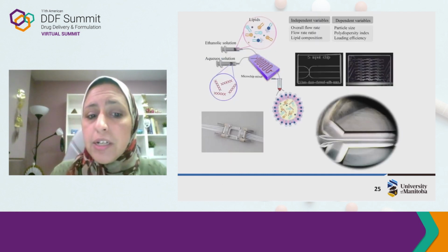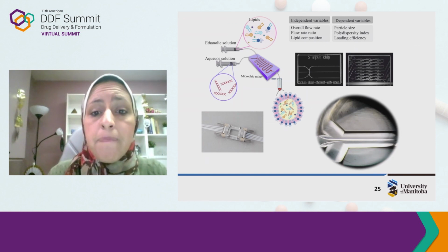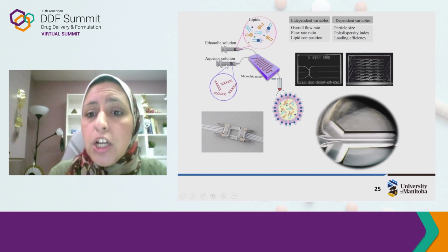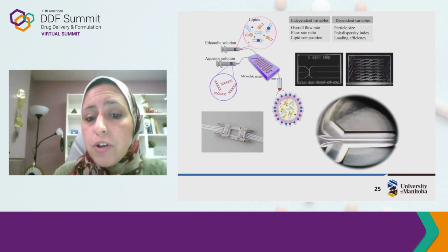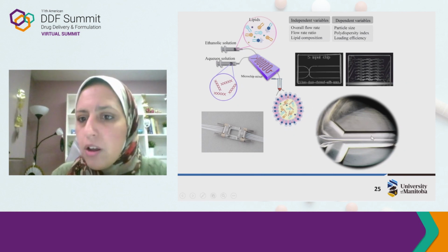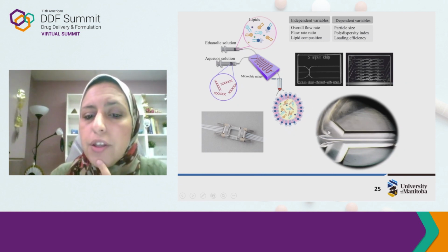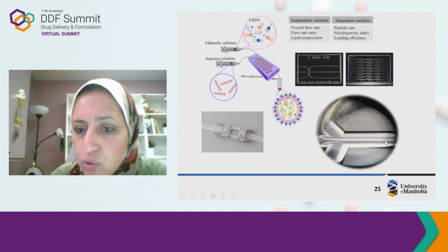And that's why we're using another setup that we have developed in the lab, also based on microfluidics, and several labs are using it already, where we are pushing the liquids into very small channels of different designs that lead also to the formation of nanoparticles. And this is a video of a run in the lab, where the two liquids, the aqueous phase and the organic phase, or the ethanolic solution, are moving here in parallel under laminar conditions, and the nanoparticles are formed in between the two layers here.